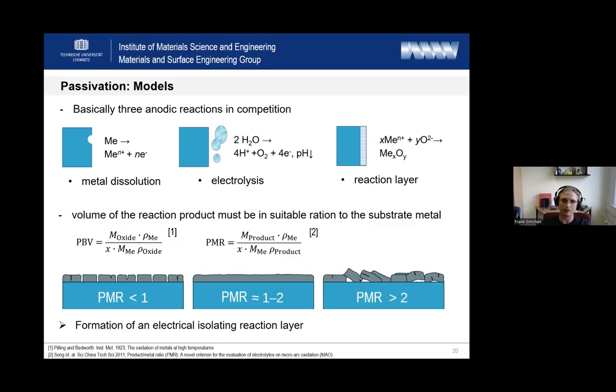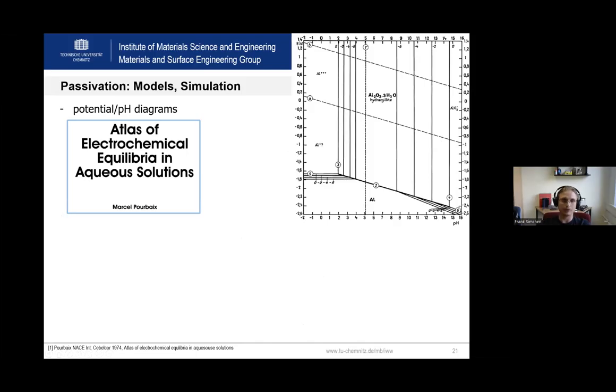work in atmospheric conditions. We are working in aqueous conditions. That's why Mr. Song just extended this idea to aqueous environment to define the product metal ratio, which follows the same idea. And this offers you geometrical boundary conditions for forming a good, stable electrical isolating reaction layer. So that's about the main model. Now it's good if you are able to simulate such stuff before you prepare 10 liters of electrolytes to find out that the system is not working.